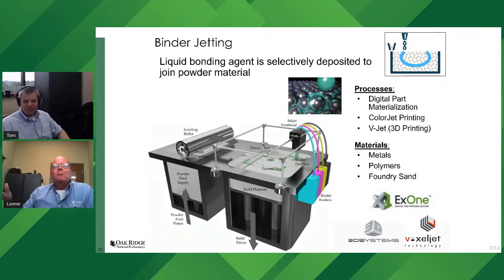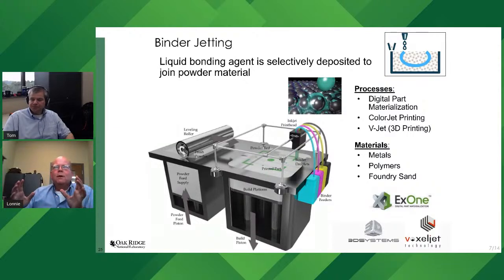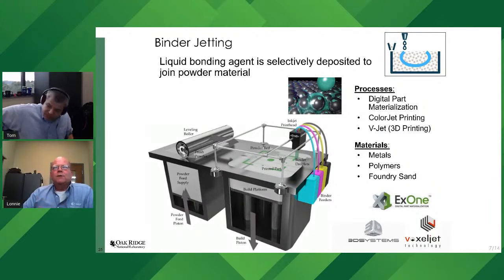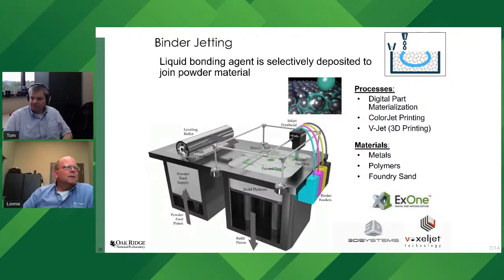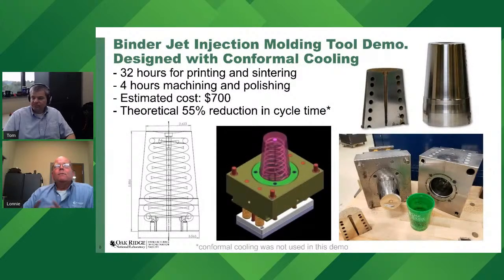There's a lot of work on the post-processing, but this is a room temperature process, so you're not battling residual stress. When you do heat it up, it's done in a uniform fashion, so you don't have to battle the warping and curling. You can also use, instead of back infiltrating through a liquid metal, gas infiltration, chemical vapor infiltration. So you put it in a chamber, pressurize it, heat it up, and that gas will turn to a solid, so you can get a solid. Like for ceramics, it's great for ceramics. Next slide.